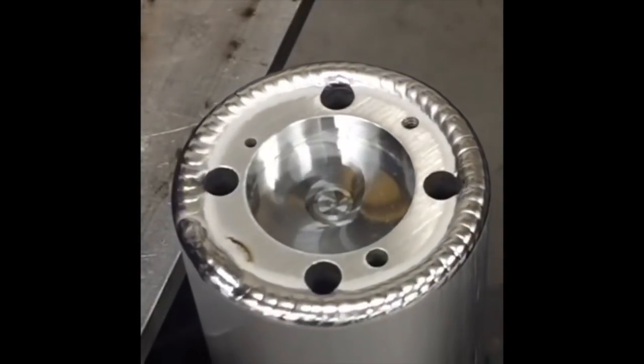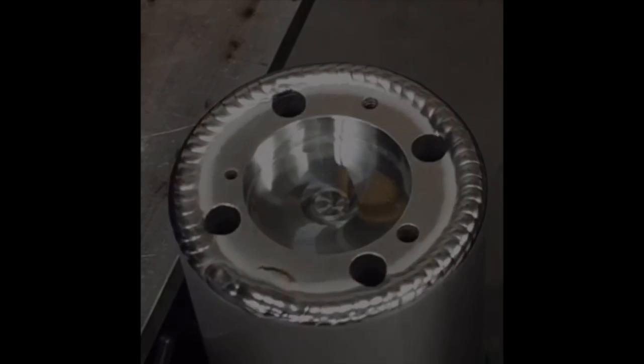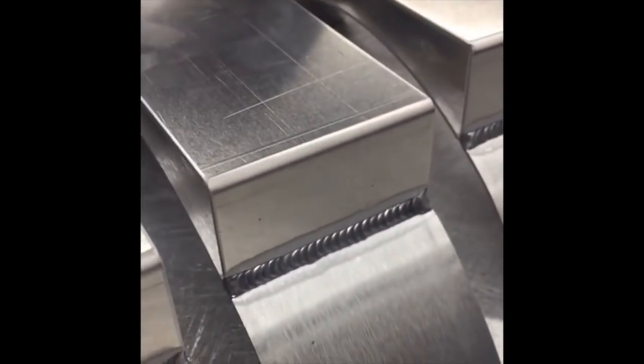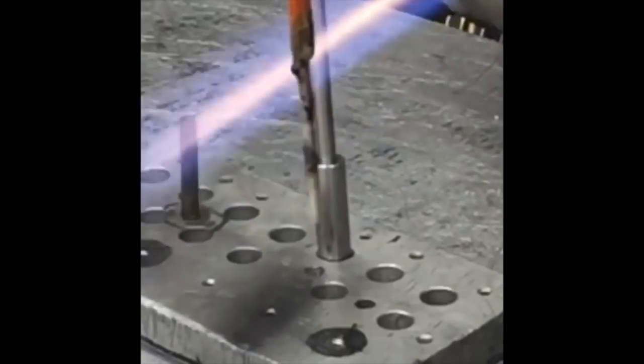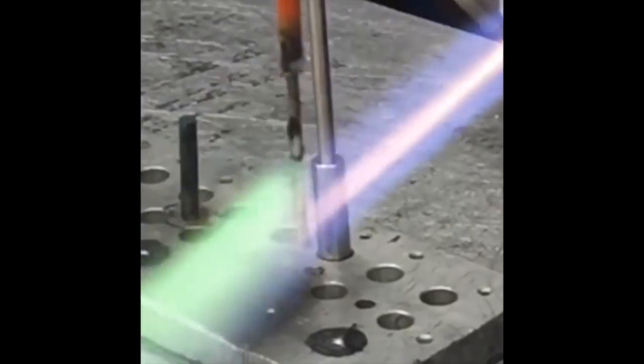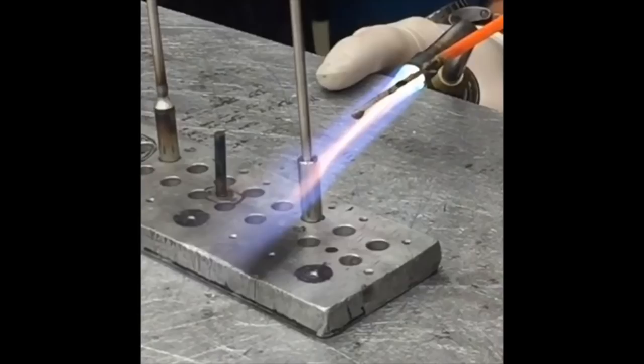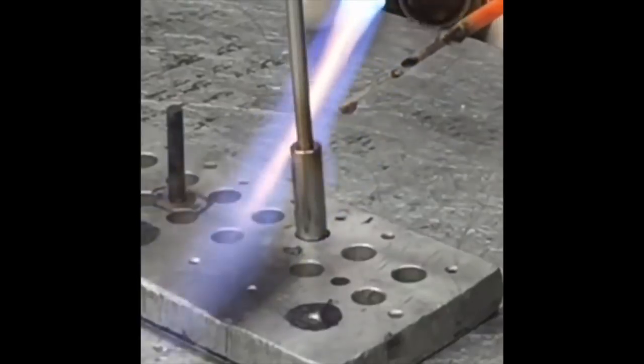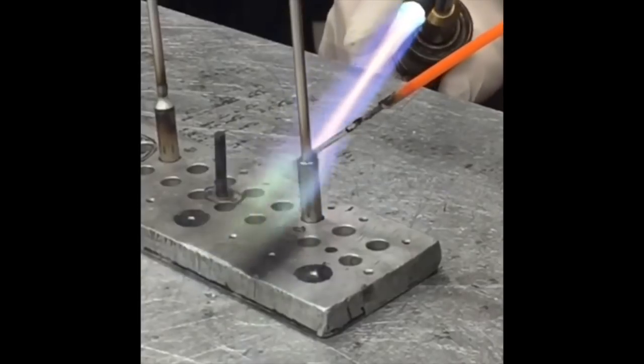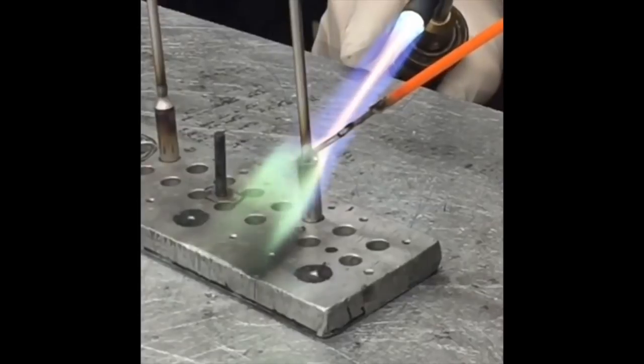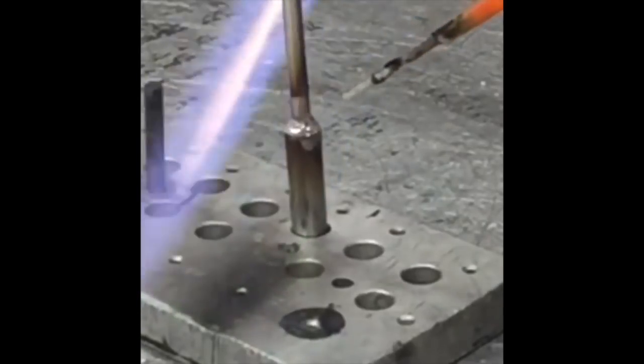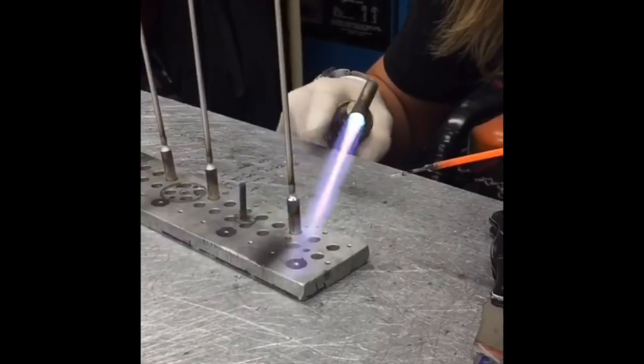For that small thin wall stuff, I like to put about a 20 to 25 degree long taper, because I don't want it to melt the metal away. I want it to kind of fan out, and since it's such a small material to work with, I want it to be as easy as I can. Since it's going to put a more shallow weld, I'm not going to blow that tube out so easily. It allows the weld to fan out so I can see it more, because I don't use magnification or anything to weld those. I just hand turn them across my table, and it allows me a little bit more ease to complete those welds.